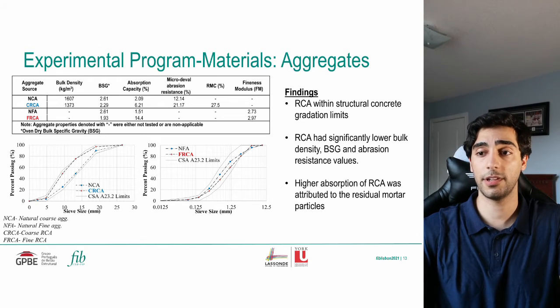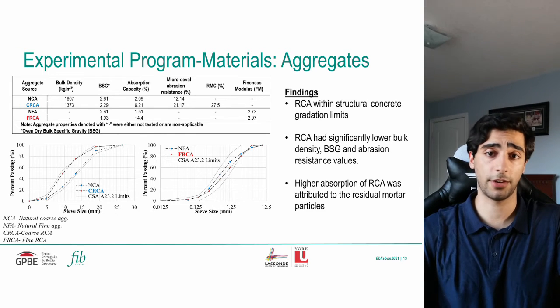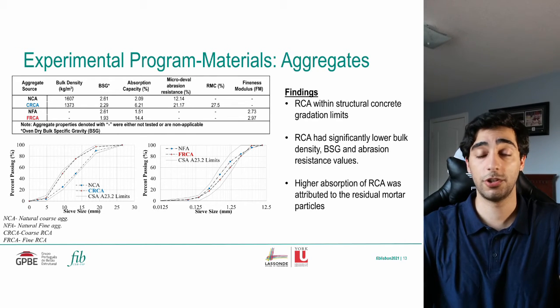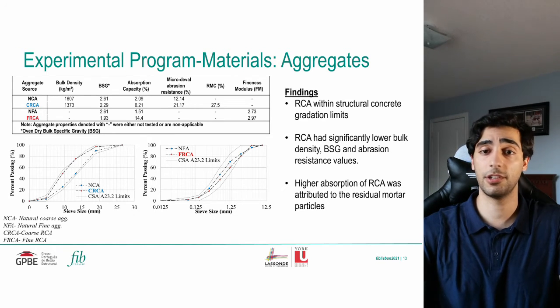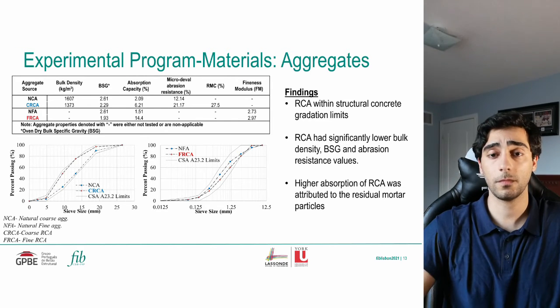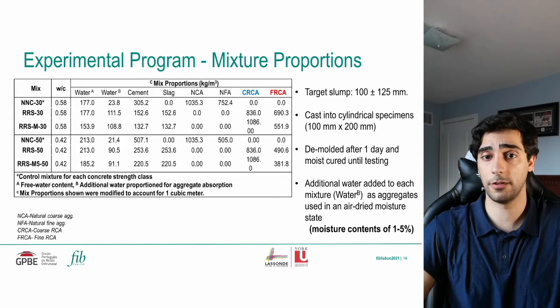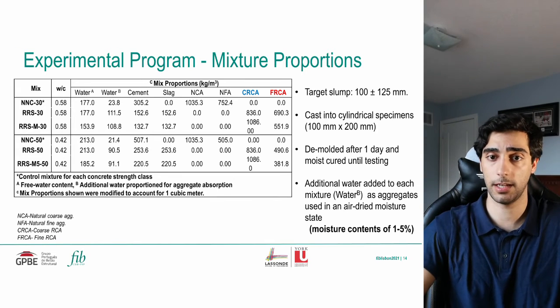However, in terms of the properties, the RCA had significantly higher absorption capacity, lower bulk density, lower bulk specific gravity values, and lower abrasion resistance values relative to the natural aggregate sources. It should be noted that the higher absorption properties and the lower density values of the RCA sources is attributed to the residual mortar fraction within the recycled concrete aggregates. Now, moving forward, the mixture proportions for the concrete mixtures are provided in the table below.